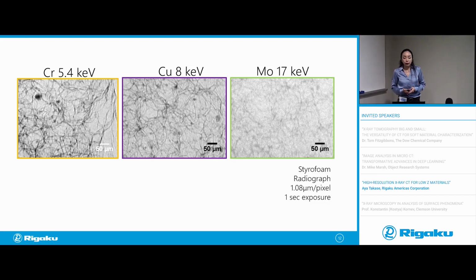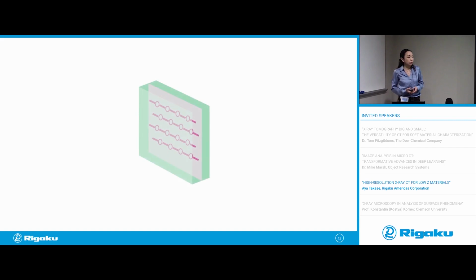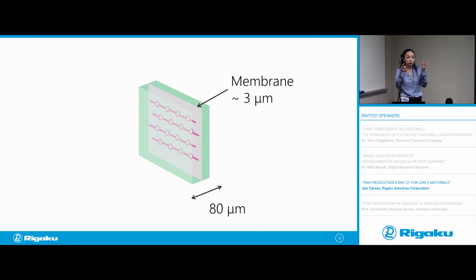I want to show you another example of this sample. This one is on organic film, and it is only 80 microns in thickness. It has a 3 micron thick membrane filter sandwiched in between different kinds of organic films. And because the whole thing is organic, there is not a lot of density contrast between the membrane filter and the sandwiching films. The whole thing is only 80 microns thick, so it's not going to absorb a lot